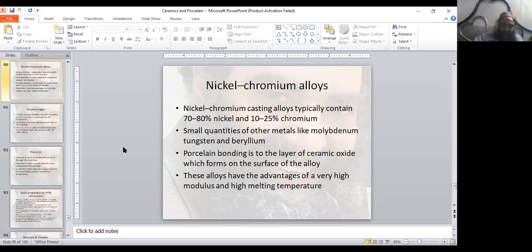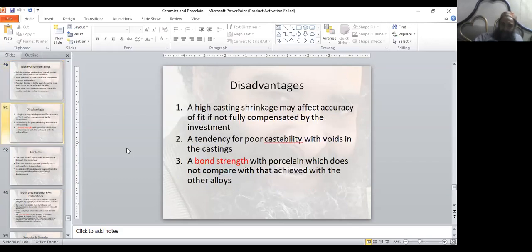Now the nickel-chromium alloys. Nickel-chromium casting alloys typically contain 70 to 80% nickel and 10 to 25% chromium. Small quantities of other metals like molybdenum, tungsten, and beryllium are also there. Porcelain bonding is to the layer of ceramic oxide which forms on the surface of the alloy. These alloys have the advantage of a very high modulus and high melting temperature. Disadvantage is the high casting shrinkage, which may affect accuracy if not fully compensated by the investment. A tendency for poor castability with voids in the castings. A bond strength with porcelain which does not compare with that achieved with the other alloys.